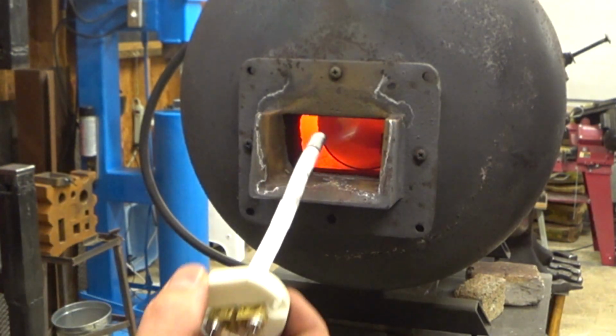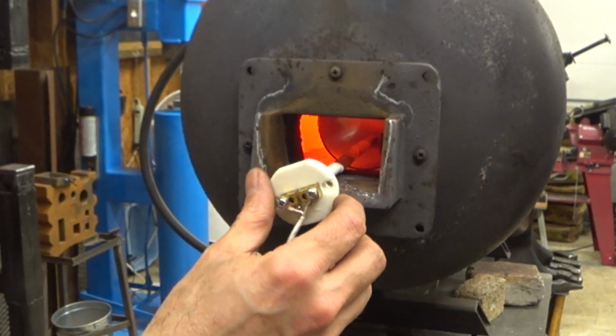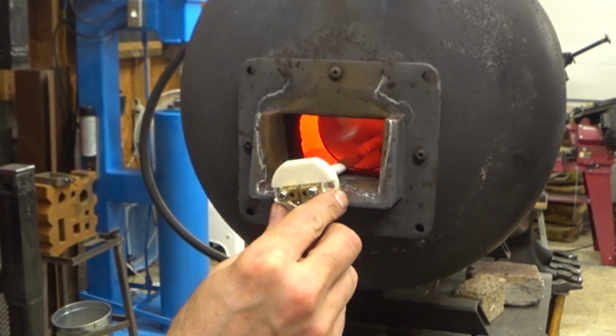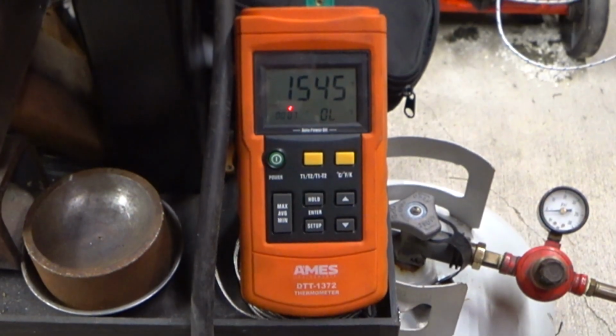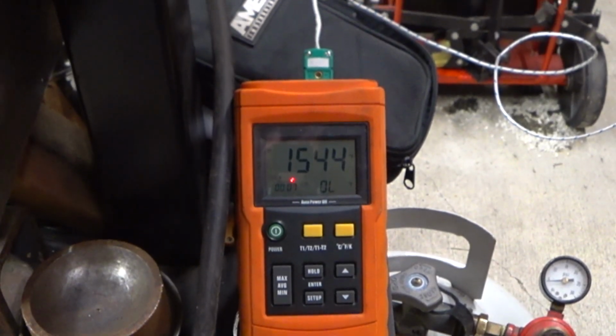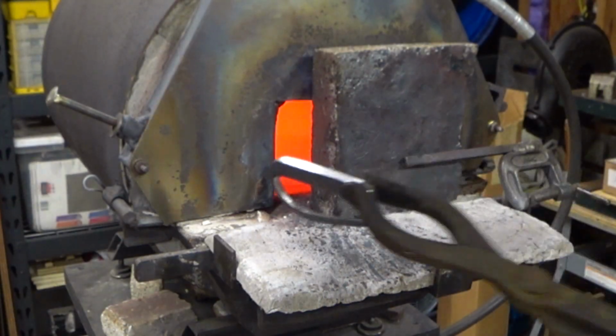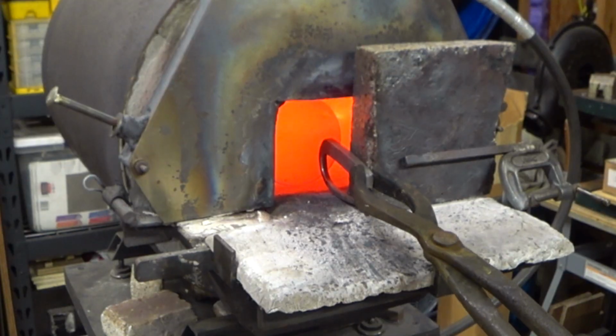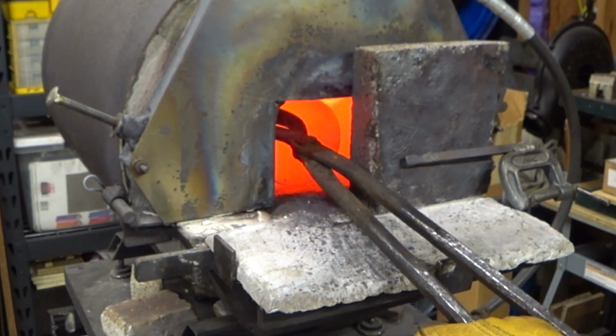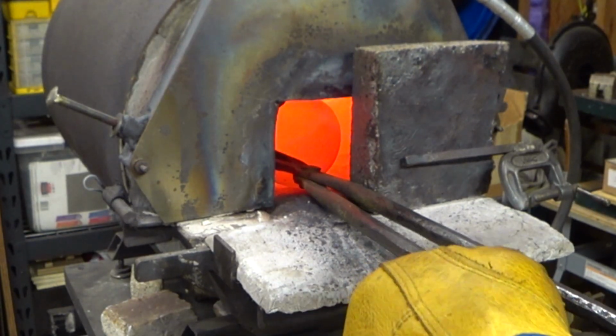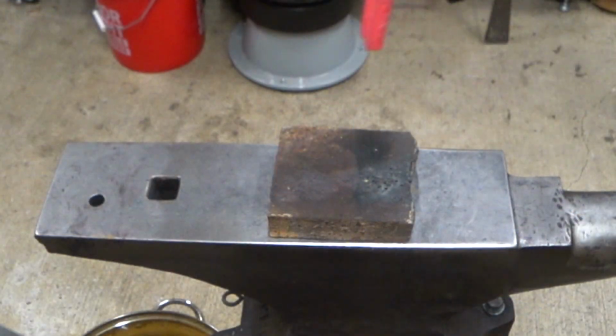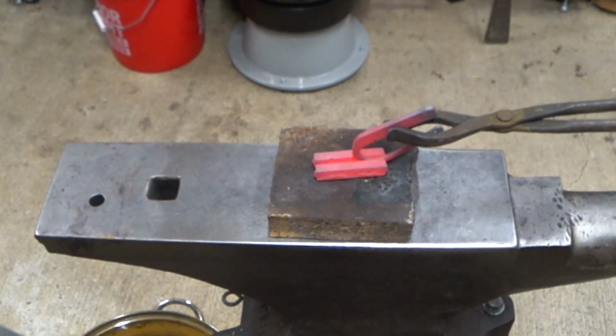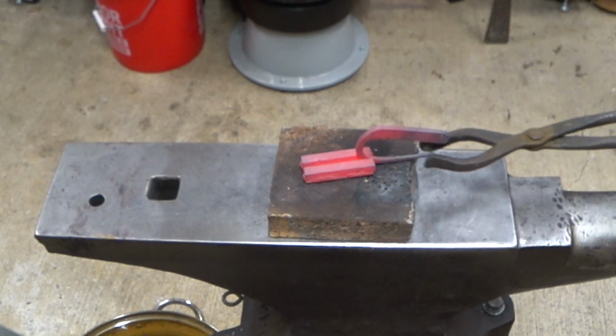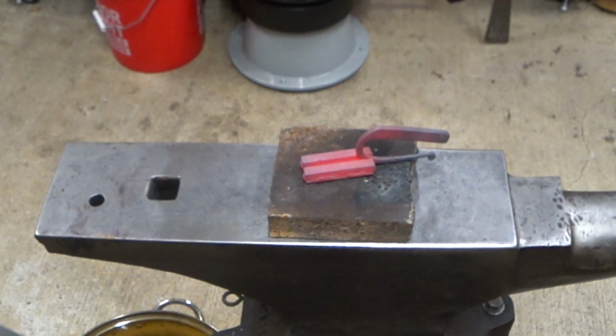From the other end of the forge, I'm placing a thermocouple into the stainless steel tube so that I can monitor the temperature throughout the heat treatment process. Although it's not strictly necessary, I don't think, for a tool like this, I'm going to go ahead and do a normalization cycle at around 1550 degrees Fahrenheit. The normalization cycle is completed by cooling the item in still air.